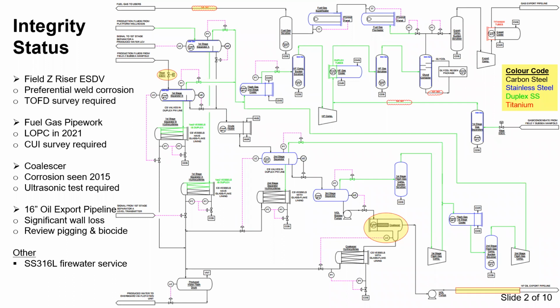Off screen, another thing we picked up was the stainless steel pipework that is in seawater service within the firewater system. We identified that as a key risk to pitting and crevice corrosion, and therefore, because that's in such a critical system, we recommend that as a key focal point going forward.